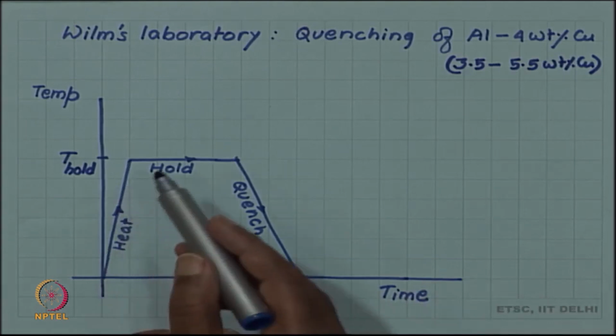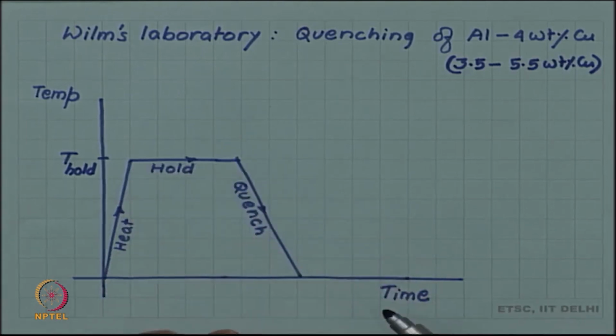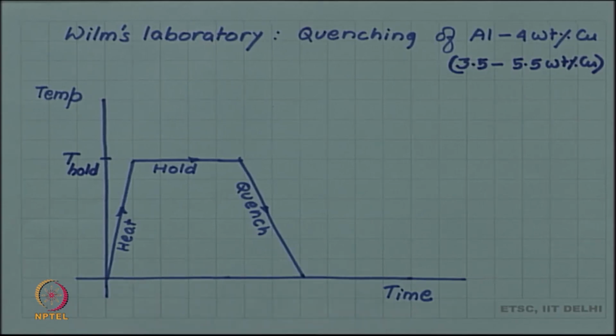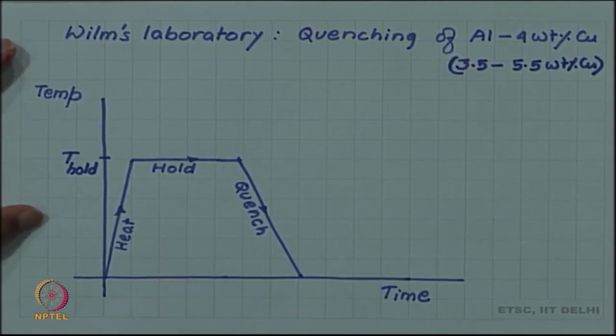He heated the sample, held it for a sufficiently long time and quenched it, but the hardness did not increase. In fact, in some cases it depressingly decreased. The hardness after quench was even less than the initial hardness he started with. So, the process was not being successful. But he thought about it, and he was a determined scientist.